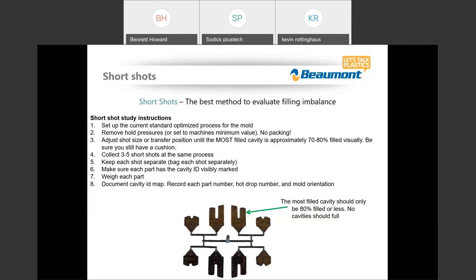And then once that happens, we have material just sitting inside that barrel, baking away. So what we want to do is get that machine back up and running, get some fresh material in there like we would be in production, and then once again gather your next short shot. You might have to do that a couple of times. It's a little painful, but I promise you it's all worthwhile at the end of the day. So we keep each short shot separate in a separate bag, and we mark these individually. We then weigh each one of these parts and document it on a cavity ID map, so we make sure that we know where that part is coming from within that runner system.